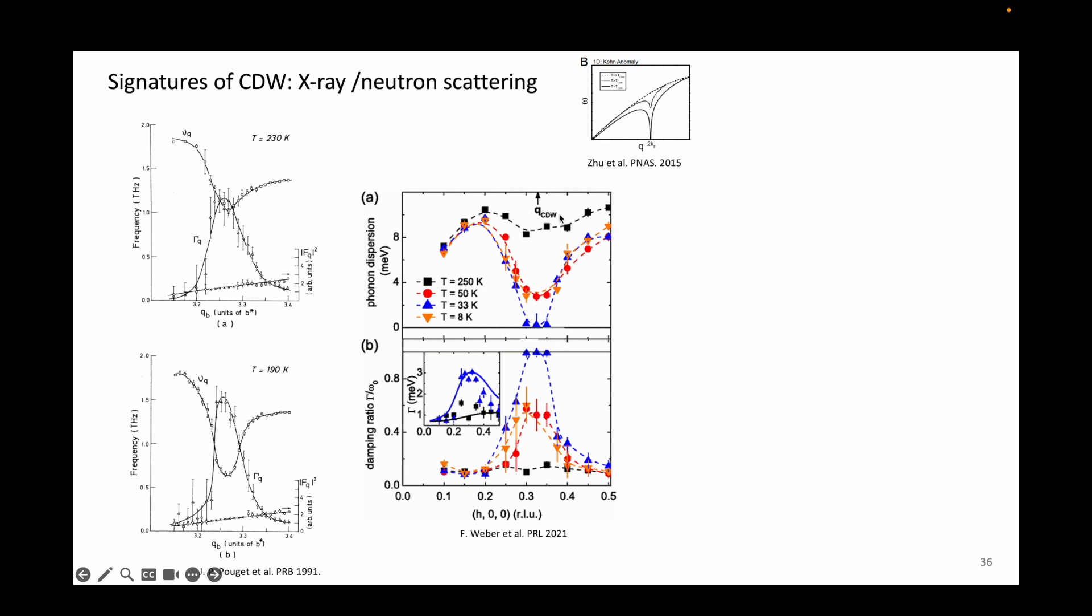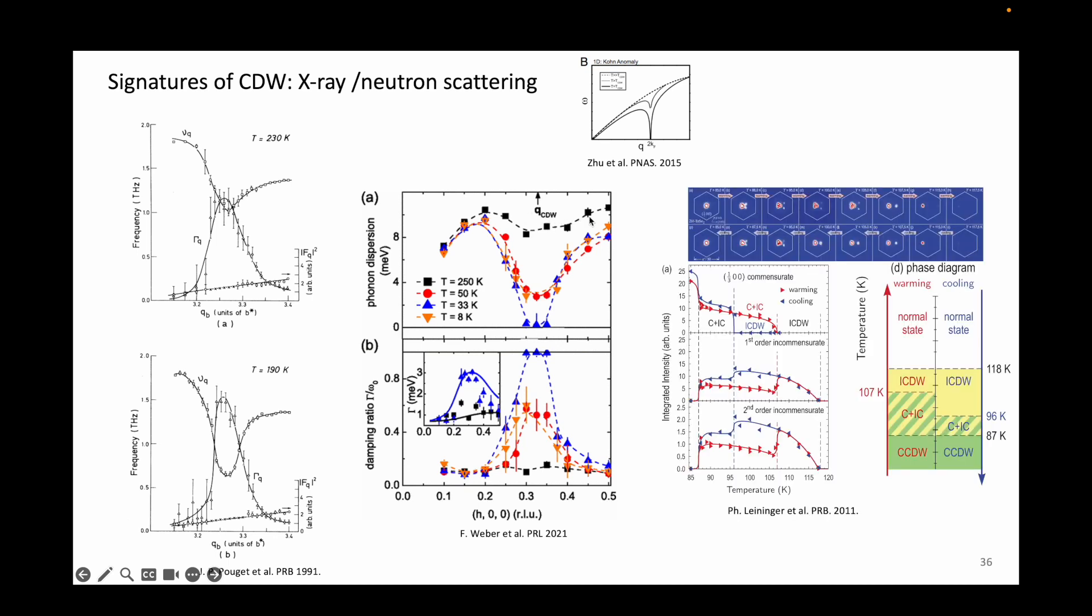On the right is an X-ray diffraction experiment on 1T tantalum disulfide which shows certain peaks associated to the charge density wave to appear. These peaks are traced over the cooling and warming cycles which show hysteretic behavior.